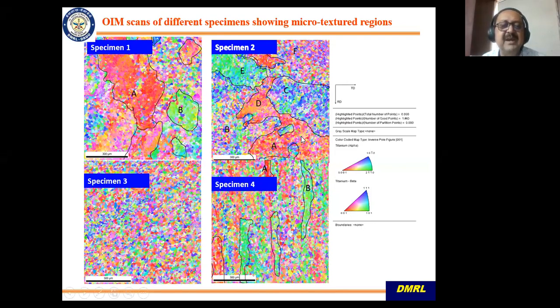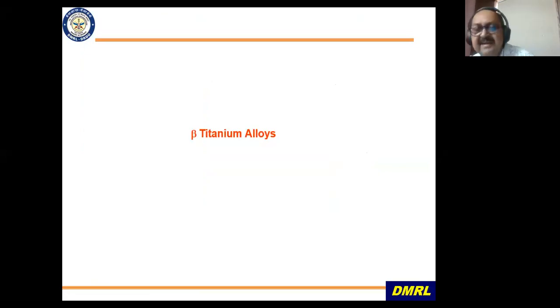Some have a very fine microstructure. This is called a random microstructure, that is in specimen 3. These are stringers which are there. Again, you can see stringer-like oriented regions, and these are larger microtexture regions, and this causes lower fatigue life, lower dwell fatigue life, and all that. Okay, so that is where I will end.